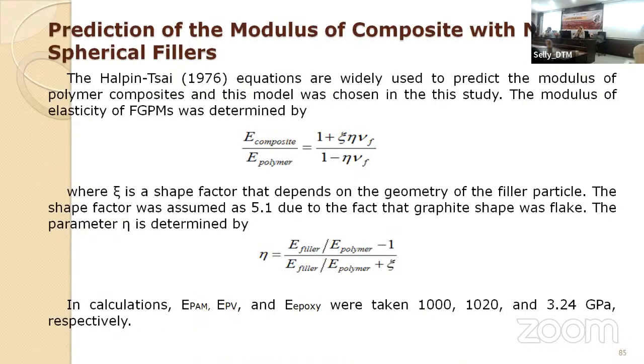And the Halpin-Tsai model is widely used to predict the modulus of the polymer composite. It was determined by this equation, in which xi, a Greek letter, is a shape factor. It depends on the geometry of the filler particle. In our case the filler particle shape was flake, so we can choose 5.1, and the parameter eta is determined by these equations. It's just a method, the Halpin-Tsai method.